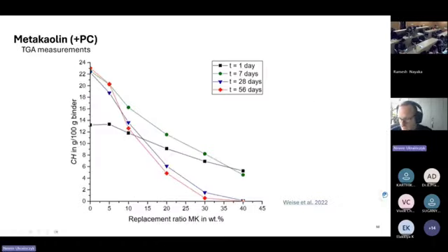And you can see exactly, yeah, of course, maybe I knew it before, that's why I put 0.4. But yeah, this exactly fits the experiment. After 56 days, this is the experiment done in our lab. We measured Portland cement replaced with 40% of metakaolin.